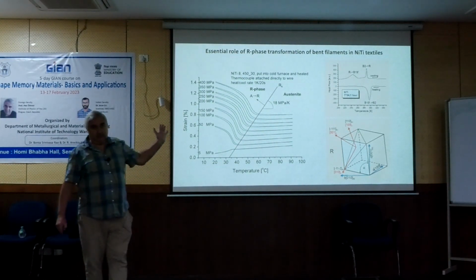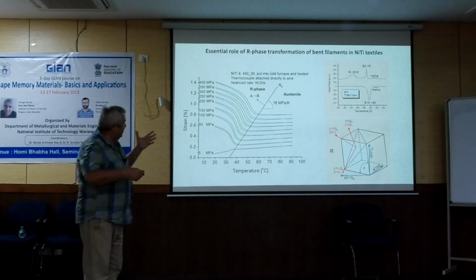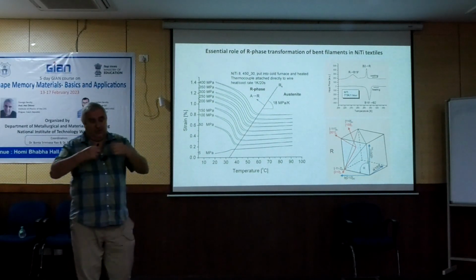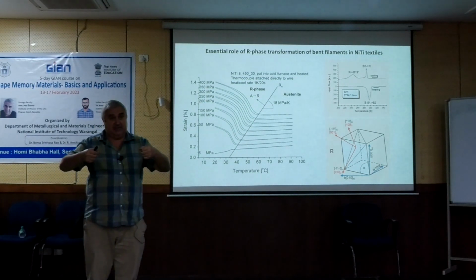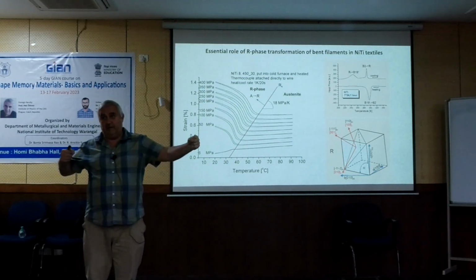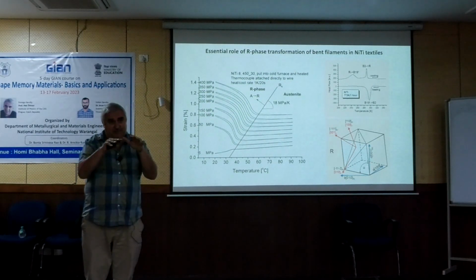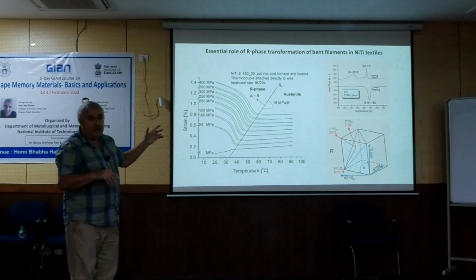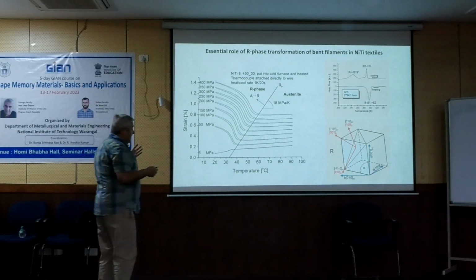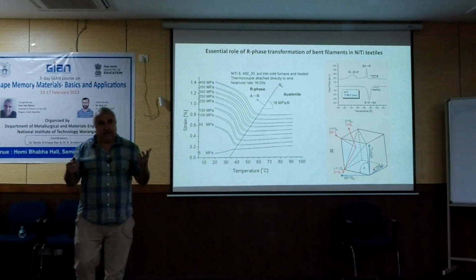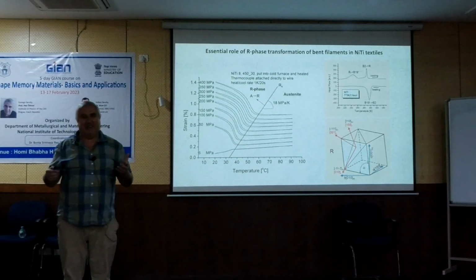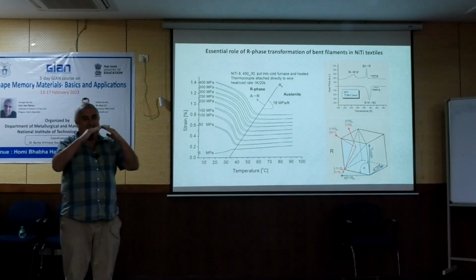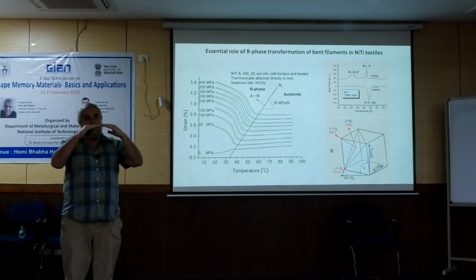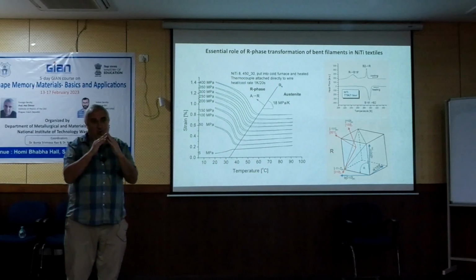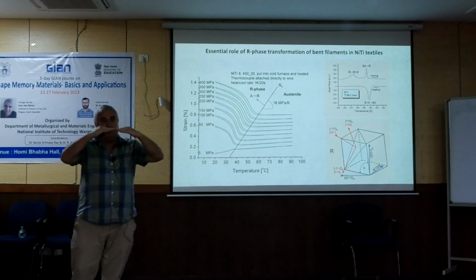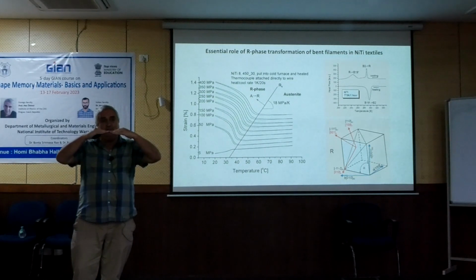Sure. Yeah, well, the beauty is that in the textile, you will never stretch the wire up to 400 megapascal. How would you do it? You would have to pull very much. But if you bend it on the surface, you will have this 1% strain. So actually, in textile form, I should say generally, all our applications are applications of the R phase, because they affect the bending stiffness very much. If there is R phase, the bending stiffness is low. If there is only austenite at higher temperature, bending stiffness is high, so it becomes flat.